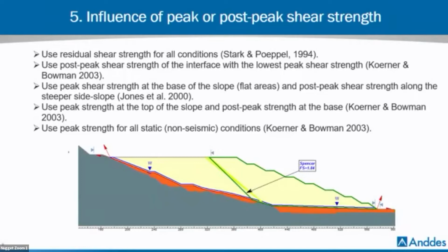Koerner and Bowman again suggest the use of the peak strength at the top of the slope and the post-peak strength. Again, Koerner suggests the use of the peak strength for all static conditions in the base and in the single zone. Well, in our research, we evaluate the use of the peak shear strength for flat zones and the post-peak shear strength for the steep zones of each pad. And we compare the findings with the numerical analysis.